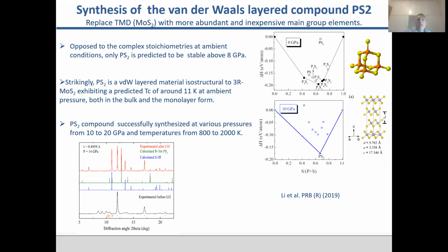And at ambient conditions, as you may see, there are a lot of compounds stable between phosphorus and sulfur, with different stoichiometries. However, they all share a common bonding. They all form this kind of diamondoid-like, if you like, or cage-like arrangement. Now, under pressure, the picture completely changes. Even at very low pressure, 10 GPa, only one compound is stable, the phosphorus sulfur 2. And the main difference is that instead of these molecular arrangements, you have layers. You have more or less this structure, which is exactly the same structure as molybdenum disulfide. So one expects the same properties since the structure is the same.